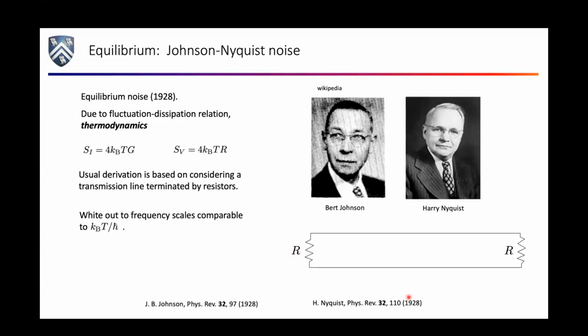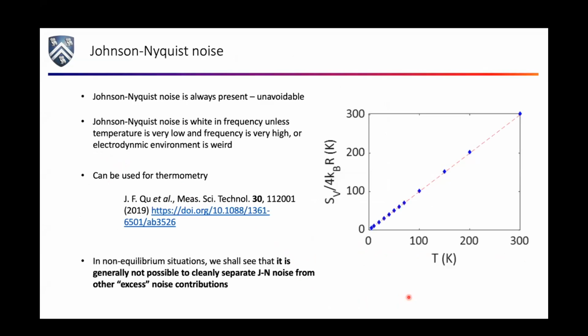The noise is white in frequency, at scales comparable to kT over h-bar. So it's always present. You can actually use Johnson-Nyquist noise as a thermometer. Here's an example where we take just a resistor and vary the temperature, measure the actual noise of the device, and look at it as a function of temperature. And guess what? It really does agree with what your independent thermometer says. So you can really do nice things here.